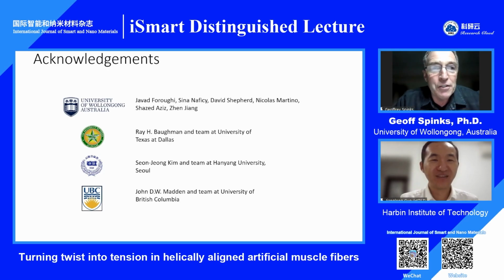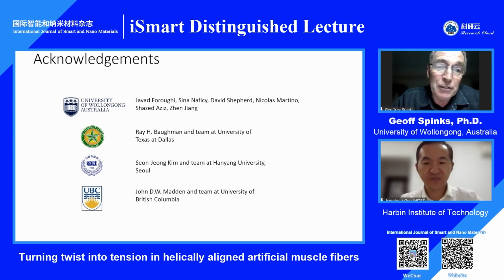Yeah, that's a great question. There were a lot of other examples of combinations of textile fibers and swelling agents that we tested that suffered that very problem, that were not very reversible and did not have very long cycle life. So I think the success of the polyester yarn with the polyacrylic acid comes down to its robustness. It seems to be quite resilient, maybe has a high fracture toughness, but it seems to be resilient to this coiling process, this supercoiling process.